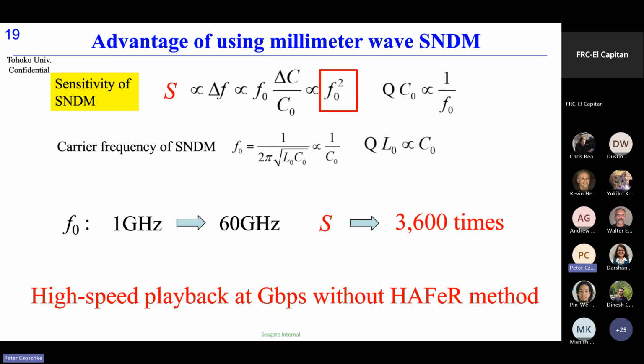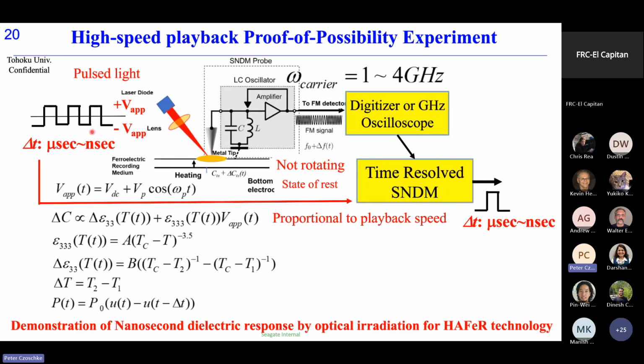But in this case, we apply the pulse light with the duration from microsecond to nanosecond, and also we don't have such a high frequency demodulator, so we directly acquire the microwave signal by using a gigahertz oscilloscope. And also, we don't have such an analog demodulator. So after acquiring the raw data, we numerically demodulate the signal, and we confirm the microsecond or nanosecond output signal.